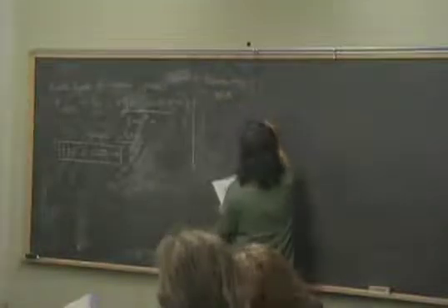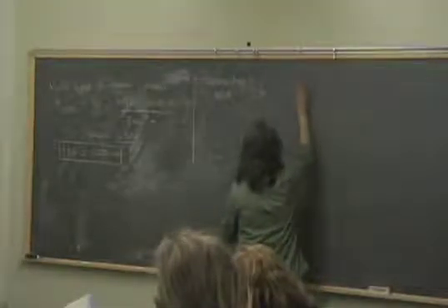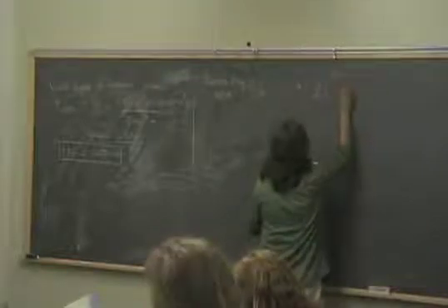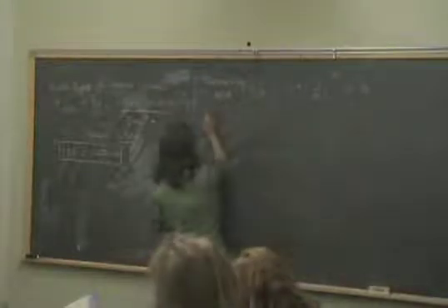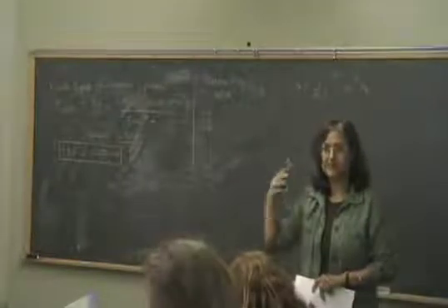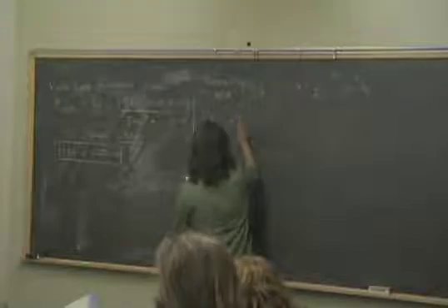Okay, now let's look at plasma frequency. Get a number for that. So plasma frequency, Ashcroft and Mermin has a nice table, and essentially for gold, so for simple metals, it is of this form, 11.4 (rs over a0) to the minus 3 halves times 10 to the 15 hertz. And for rs over a0, if you remember, rs is the mean distance between electrons. It's dependent on the density, cube root. And for gold, this is a number which is like 3.01.